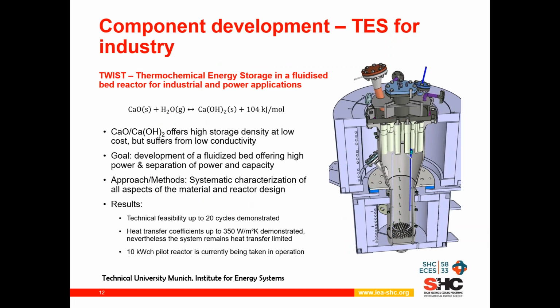How this material is then used to charge and discharge is an example here from the Technical University of Munich, as an example of component development within the task. This device is constructed as a cyclone reactor in which calcium oxide is being mixed with water vapor and then forms calcium hydroxide plus heat in the form of 104 kilojoules per mole. And the challenge with this reaction is to get the heat out at the proper temperatures and in an effective way, in such a way that all the particles containing this heat are being brought into good contact with the walls of the reactor. And then this reactor is being used to have cycling, and up until now the technical feasibility was demonstrated up to 20 cycles.